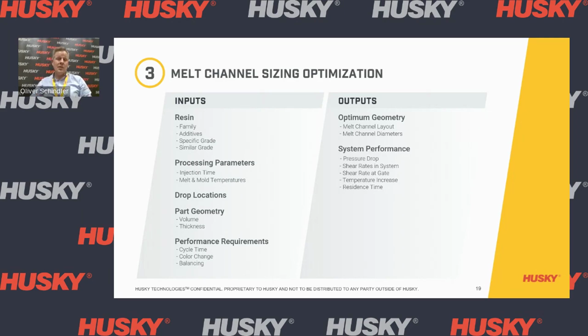And as an output, we have engineering software, which is based on MoldFlow software, calculating the system for optimized geometry of the hot runner system with optimized melt channel layouts, with optimized melt channel diameters to achieve the best possible performance on pressure drop, shear rates in the system, shear rate at the gate, temperature increase inside the system, and residence time.